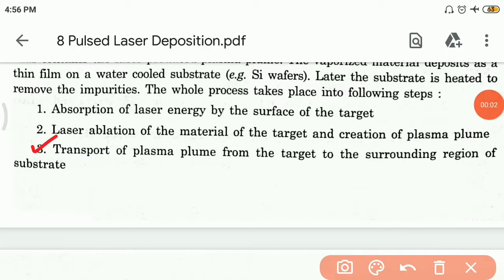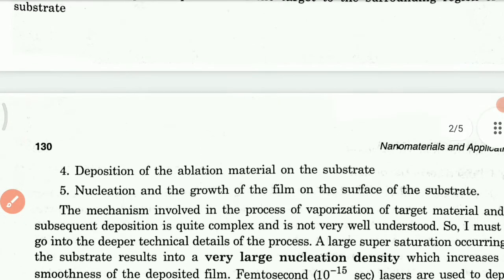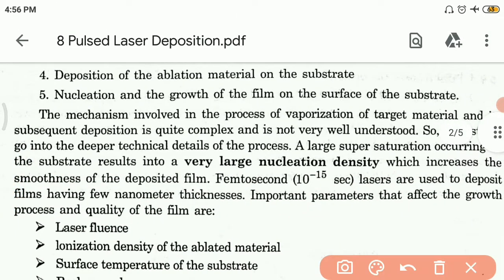Then number three, transport of the plasma plume from the target to the surrounding region of the substrate. Then deposition of the ablated material on the substrate, and finally nucleation and growth of the film on the surface of the substrate. The mechanism involved in the vaporization of the target material and its subsequent deposition is quite complex and not very well understood, so we must not go into deeper technical details. A large supersaturation occurring on the substrate will result in a very large nucleation density, which increases the smoothness of the deposited film.